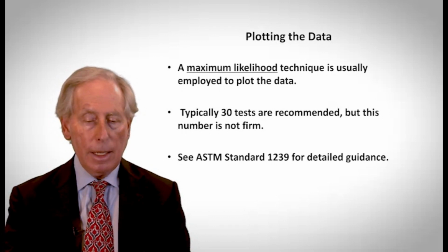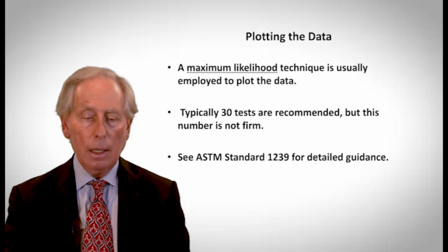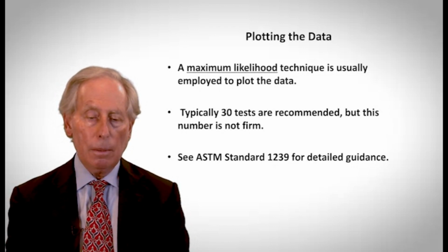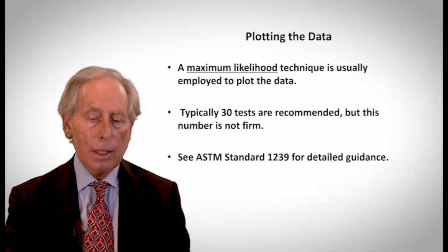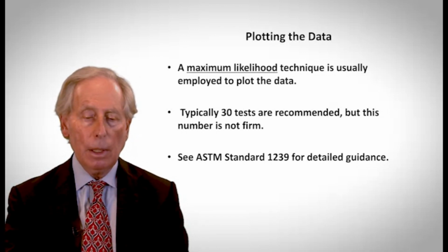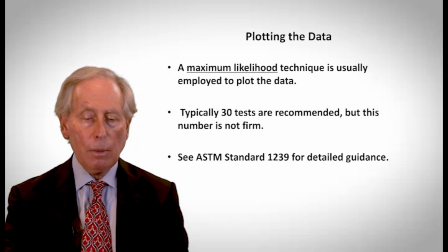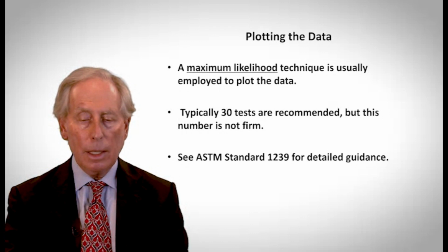There's an ASTM standard for plotting the data. It's 1239. So this tells you how to plot your data. It uses what is called a maximum likelihood technique. Again, I'm not going to go into the mathematics of what this technique represents, but it's pretty easy to put in practice for the determination of fracture stress for brittle materials. And I'm going to stick with this technique, although there are other fitting techniques that are available as well.